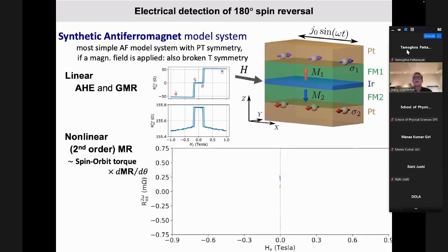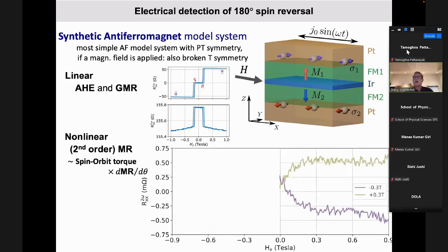And indeed, as I show you here, applying now a saturating field where you come from a negative side or from a positive side, where we know we can in principle polarize our antiferromagnetic state at zero field, we then can, by a small in-plane magnetic field, which perturbs our system just a little bit, nicely distinguish the two states at the second order magnetoresistance, which is measured here.